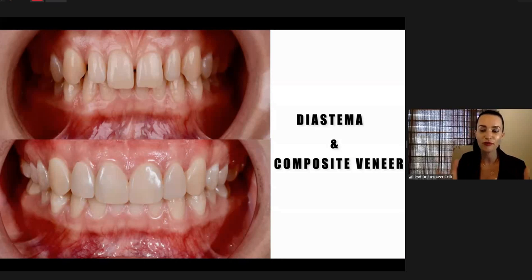Also, they have, for example, opaque shades, like typical flowables, but their main problem is the polymerization shrinkage, unfortunately, because typical flowables shrink about 3%, while conventional resin shrinks 2% or less than 2%. And also the application characteristic is completely different from the traditional composite, because you cannot stop a global composite, but also they have thixotropic property, so you can easily manipulate this kind of resin. Also, this has a different advantage in the application.